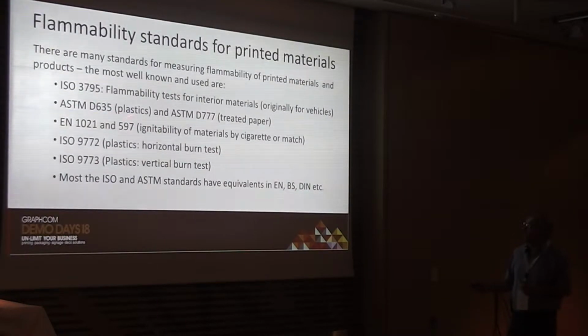Then the 635 for plastics and the treated papers, 777, that's both American. Then there's no equivalent in ISO as far as I know, or they're still being developed. EN 1021, that's ignitability by cigarette or match, that's very important, of course. Then you have some plastics for horizontal burn or vertical burn test that has to do with which way the draft, the potential air draft may be coming from.